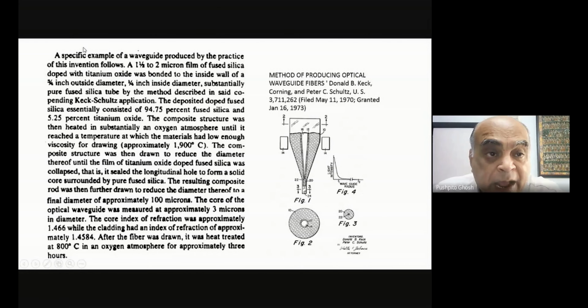And they're giving a specific example so that you can get some idea of the numbers. A specific example of a waveguide produced by the practice of this invention follows. A 1 1/4 to 2 micron film of fused silica doped with titanium oxide was bonded to the inside wall of a 3/4 inch outside diameter, 1/4 inch inside diameter, substantially pure fused silica tube by the method described in said co-pending Keck-Schultz application. The deposited doped fused silica essentially consisted of 94.75% fused silica and 5.25% titanium oxide.